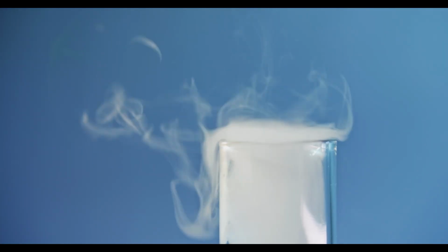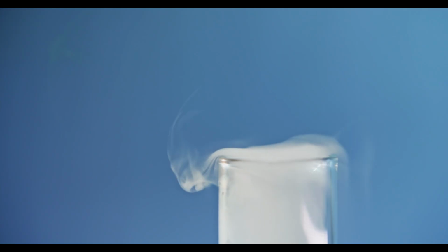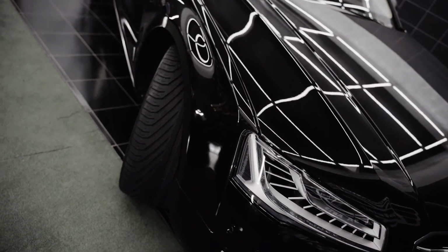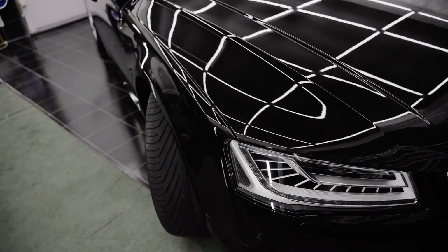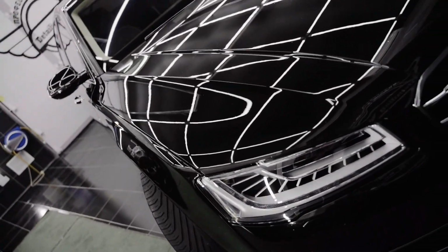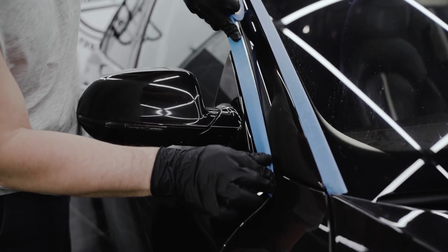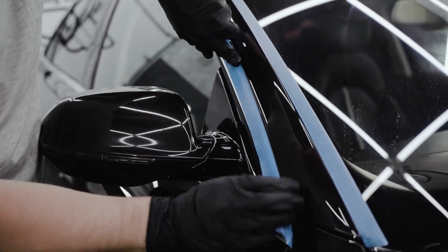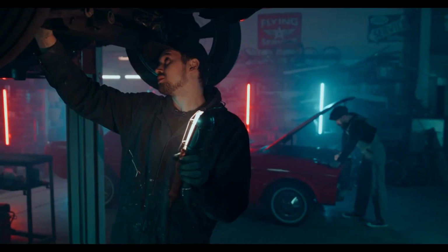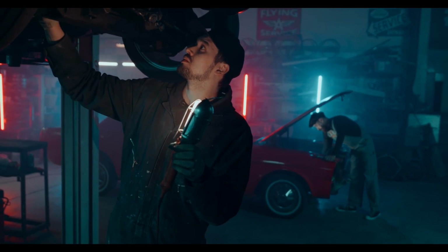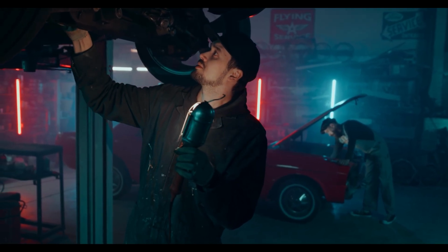After a perfect sanding until grain 3000, the headlight remains with a silky matte appearance. It is in this moment when the vaporization cup enters into play. The polymerizing liquid, upon heating, releases a dense vapor that, upon touching the cold polycarbonate, melts the micro scratches of the sanding and deposits a new layer of liquid polycarbonate resin that solidifies instantly.